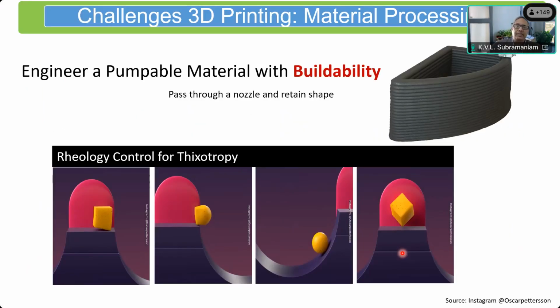The other property which deals with buildability brings in something called thixotropy. And this is where we, as concrete engineers, started realizing that we really have to understand rheology of the material. Rheology of the material is understanding how materials flow. And thixotropy is like this behavior that's shown here. So the material itself is resistant to flow until you push it. But once you push it and it starts flowing, it basically flows very easily. So you see what's happening here. It's like a rectangular shape, or it's like a cubic shape. Once it's forced to flow by tipping it over this edge, it takes a circular shape and basically glides on the surface very easily. And the minute it comes on the other side, it basically goes back and keeps its shape. So what's happening here? Internally, the structure is initially in that gel-like state. It won't flow unless you pressure it. That is the tipping point here.